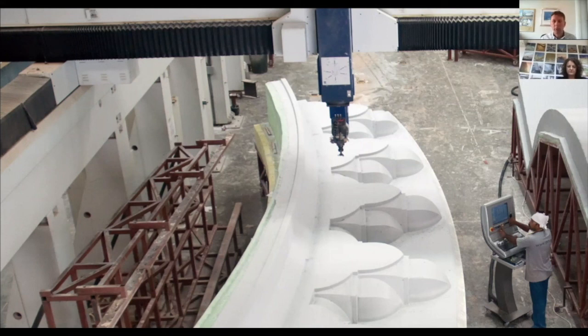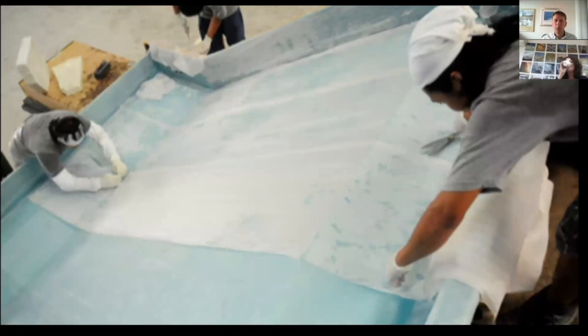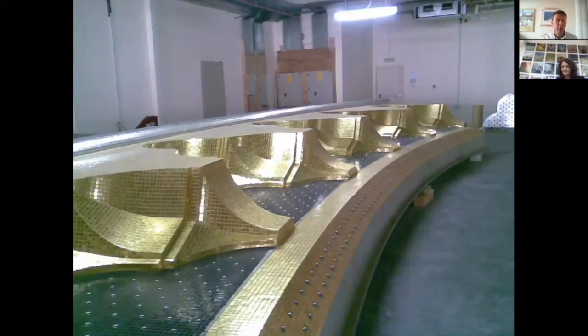The parts are moulded, so first we have to make a mould. In this case we were using CNC machines to cut the moulds. The parts were manufactured using a wet lamination process, where you take a wet resin system and combine it with dry fabric in the mould itself. We used a specific fire-retardant resin system developed for the project. Because the fire-retardant additives made a relatively thick resin mixture, we used a wet-out machine — where the fabric is passed through a bath of resin to pre-impregnate it. The parts are then laid up into the mould and cured in an oven at about 50 degrees C.